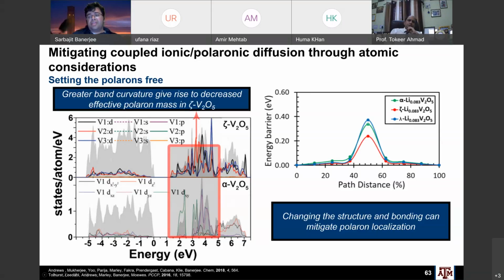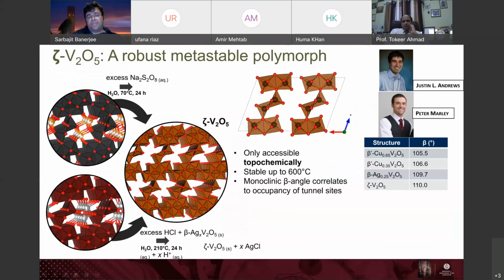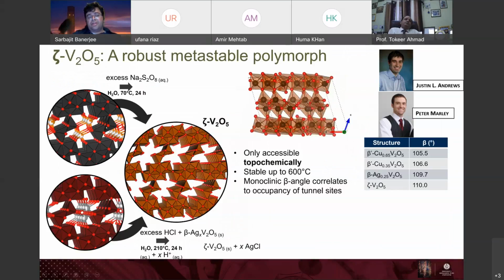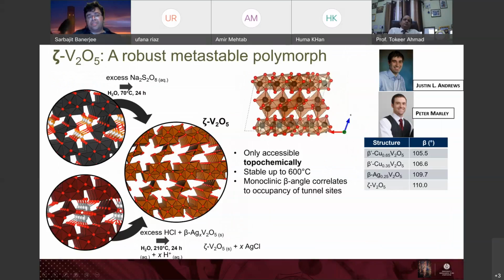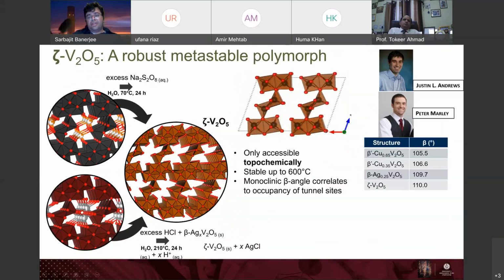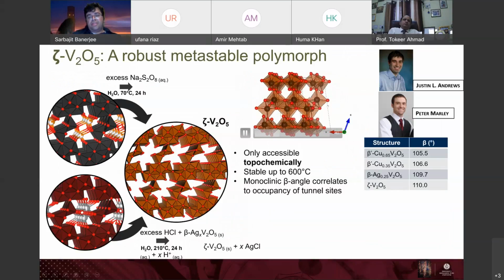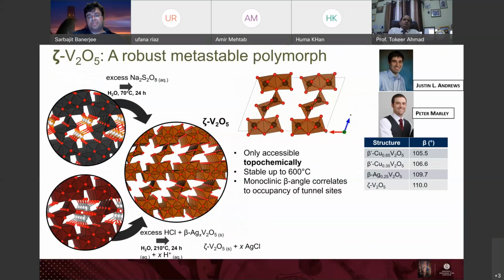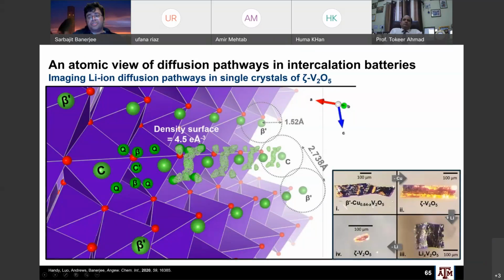So you can see here, this is the alpha phase. We can reduce the polaron formation barrier in the zeta phase, right? So changing the structure and bonding can greatly change the fundamental mechanisms of ion diffusion by changing the coordination environments and by changing the activation energy barriers. So zeta V2O5, this is how we make it. Again, we can make this by starting with copper V2O5 or silver V2O5, and we can take the copper ions out or silver ions out, and we can stabilize this empty structure,